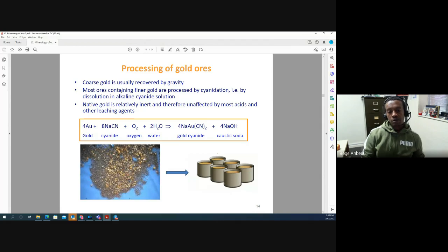Okay, so again, I mentioned cyanidation a couple of times already. That's at the moment anyway. That is the typical method for processing gold concentrates, because we know sodium cyanide dissolves the gold really well, but for that to work, you need oxygen. And therefore, now you have a big leach tank with cyanide in it. You add your material, you agitate for a few days typically.